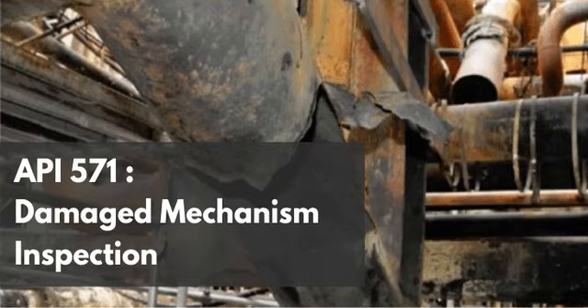But it is a razor-thin tightrope. If you inject too much ammonia, or if it concentrates in specific pockets of the system, you solve your general corrosion problem, but instantly introduce the exact chemical environment required for ammonia stress corrosion cracking. It's unbelievable. You trade a visible, measurable thinning problem for an invisible, sudden cracking problem. That's exactly what happens. But from what I read in the API standard, the ammonia alone isn't always enough to trigger aggressive cracking.